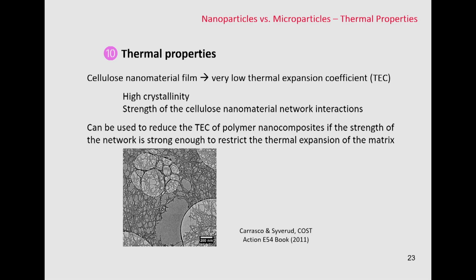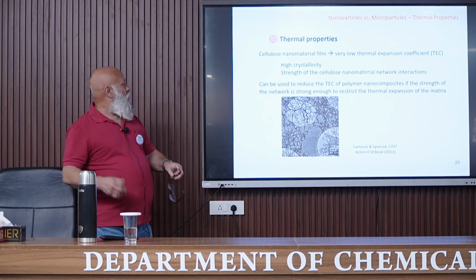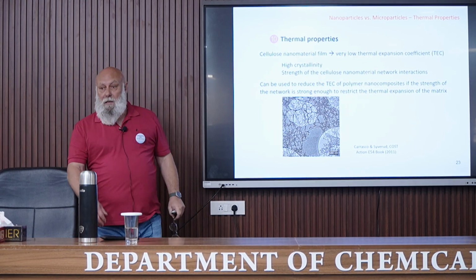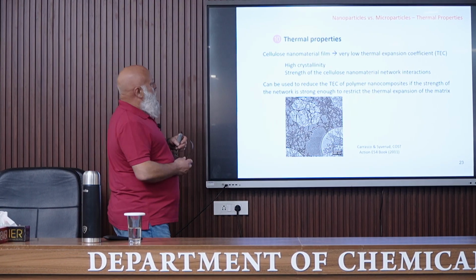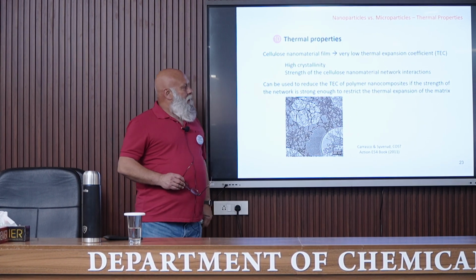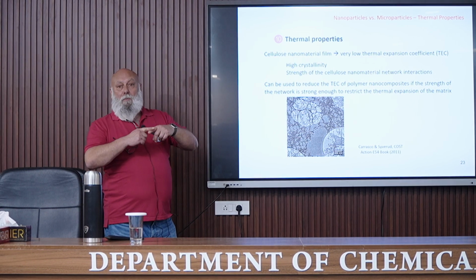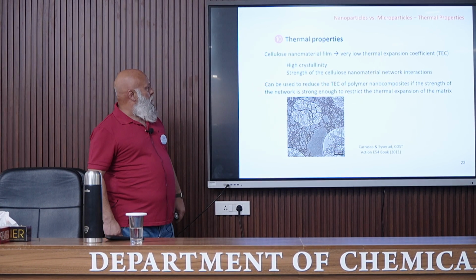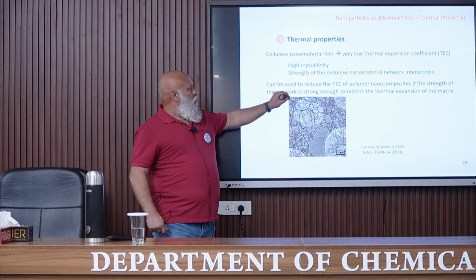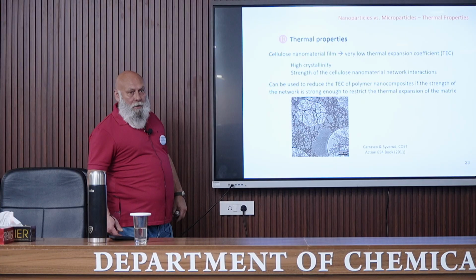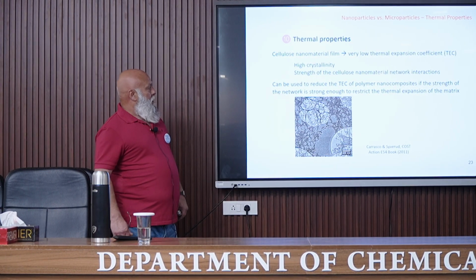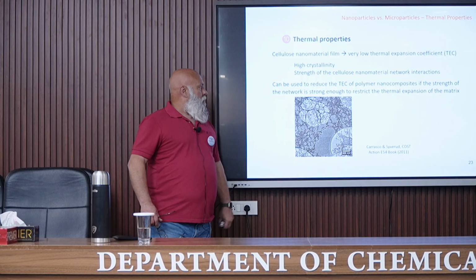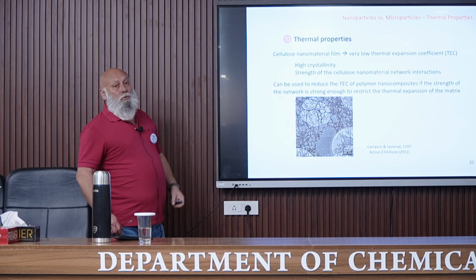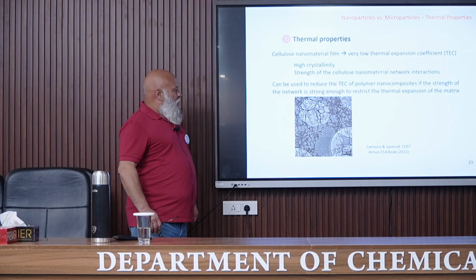So thermal properties. When preparing a cellulose nanomaterial film, it is observed that the thermal expansion coefficient is very low. This is explained by the high crystallinity of the nanoparticles, but also by the strength of the cellulose nanomaterial network interaction. So, of course, we have some hydrogen bonding between these nanoparticles. And this property can be used to reduce the thermal expansion coefficient of polymer nanocomposite when you're mixing these nanoparticles with a polymer, if the strength of the network, of course, is strong enough to restrict or to limit the thermal expansion of the matrix.